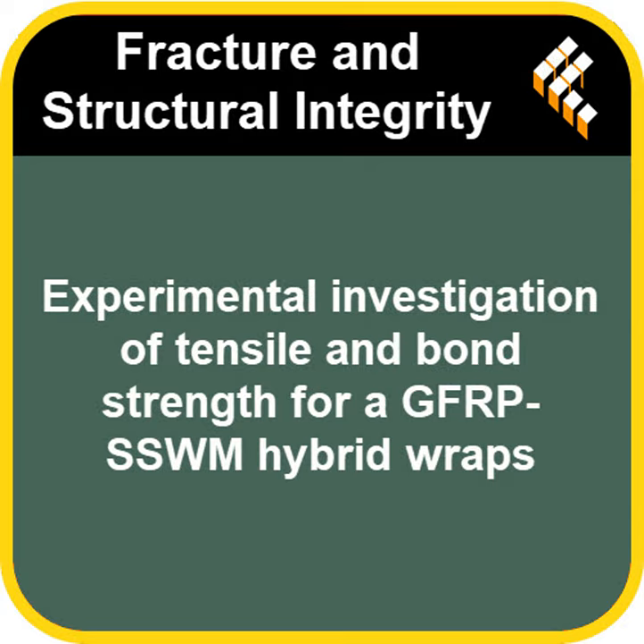And they changed things up within those tests, right? What were the key variables? Two main things. First, the number of reinforcement layers. They looked at 2 layers versus 3 layers. Okay, layers matter. Definitely. And second, the type of epoxy glue holding it all together. They compared 2 kinds, Sikadur 330 and Sikadur 30 LP. Ah, the adhesive. That's always critical. Absolutely. These variables let them pinpoint what really affects performance.